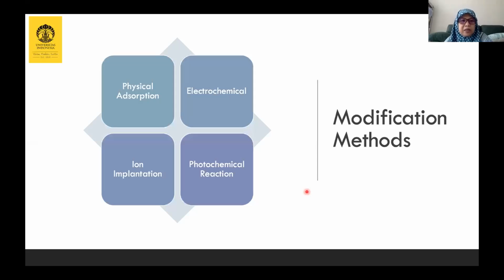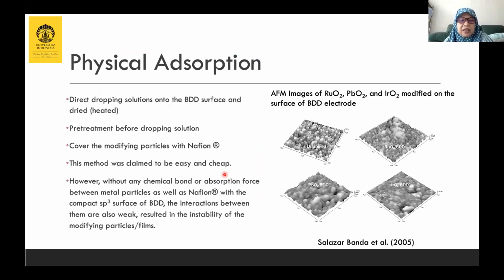Then how do we modify diamond? Actually, we can modify with physical adsorption, electrochemical deposition, ion implantation, or photochemical reaction. Physical adsorption is the simplest one. Generally, we can just drop solution onto the diamond surface and then dry or heat it if necessary. But it generally produces very unstable films that are easy to remove from the surface of diamond.